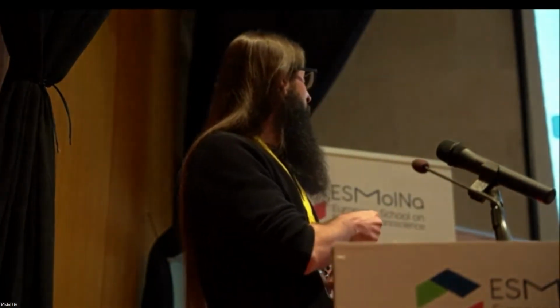And then the other thing that Mario is asking is why in that case cobalt and not iron or nickel are used? Yeah, we have tested the activity of this Weakley sandwich with manganese, but manganese is not stable. We have tested with iron. Iron is a bit less active than cobalt, but of course, iron is more interesting from the point of view that there is more iron in the crust. So yeah, it's also active, but not as active as the cobalt one. And somebody else tested with nickel, but it's not active.